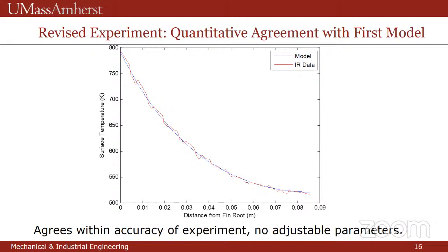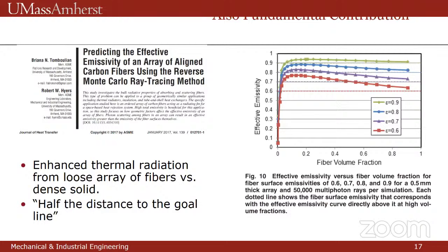So in the course of this project, we also made an interesting discovery. We looked into what happens with the emission of radiation, light photons, from this kind of furry array of fibers. And it turns out you get an enhancement in the emissivity that's about half the distance to the goal line. So if you look at the red curve, the dashed line at 0.6 is what you'd get from a flat fin with an emissivity of 0.6. And if you have an array of fibers, then depending on the fiber volume fraction, you can get up to almost 0.8 for the emissivity, almost half the distance to 1. And this is a property of the multiple scattering from the depths of this furry array of fibers.